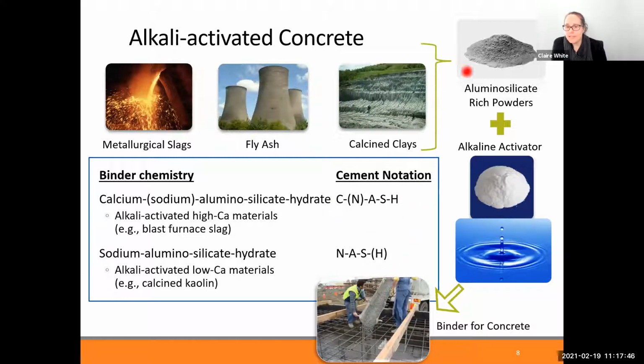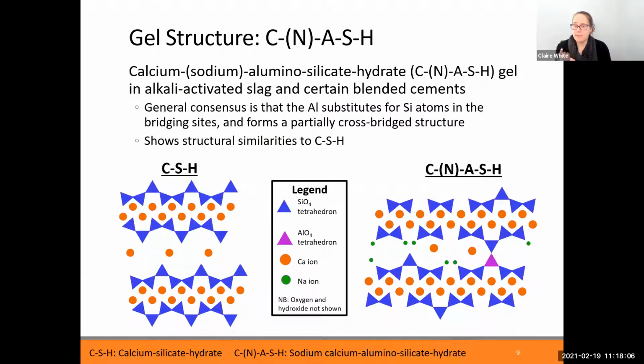If your aluminosilicate doesn't have much calcium in it, then you end up with what's called a NASH gel if you're using a sodium activator. So it's a sodium aluminosilicate hydrate gel. We also do a lot of research on systems that contain this NASH gel as well. But today I'm going to be concentrating on the CNASH gel. It is important both for blended Portland cements, where sodium's going into it, and also for certain types of alkali-activated concrete. There is a general consensus that the CNASH gel has similar types of local bonding environments to the original calcium silicate hydrate gel, but there's differences in terms of the silicate chain lengths.